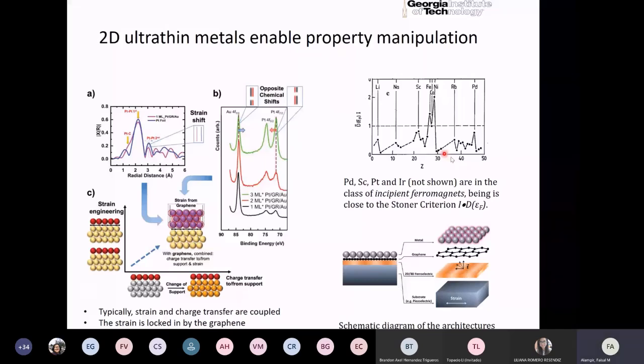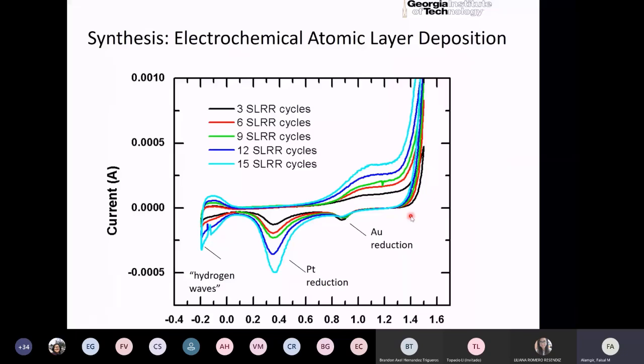So what we do is we grow atomic layer films of these catalysts by using a method of layer by layer deposition. The acronym here stands for surface limited redox reaction, SLRR. And by the number of cycles of this, you can essentially control how many layers of platinum we are growing.